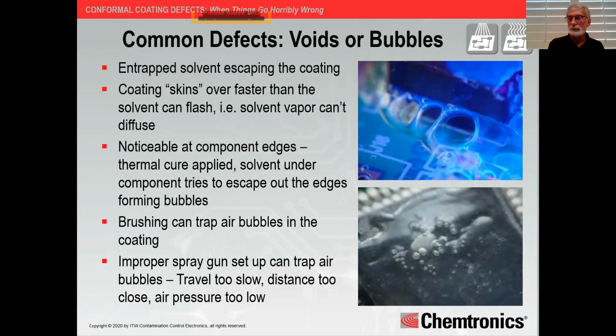Is it a defect? Depends on your criteria. According to 610A, maybe. If it satisfies that bridging criteria, then yes. But let's say it's way out on the edge of the board somewhere. It's in a non-populated, just a blank area. It's uninhabited by components. You may have a bubble. Is it a defect? Well, it depends. If it does not fit that criteria, if it's not bridging lands, adjacent components, whatever criteria you have set up, then it's a process indicator. Something has gone wrong in your actual application of that process, and it should be addressed and it should be resolved, but it's not a defect.